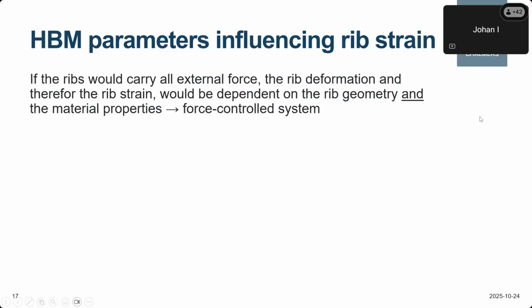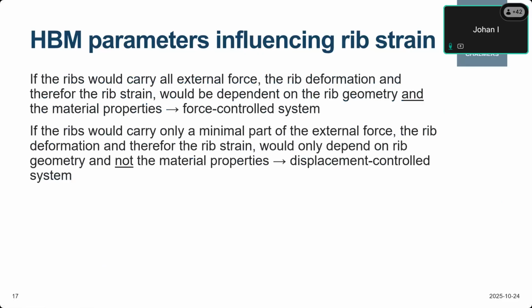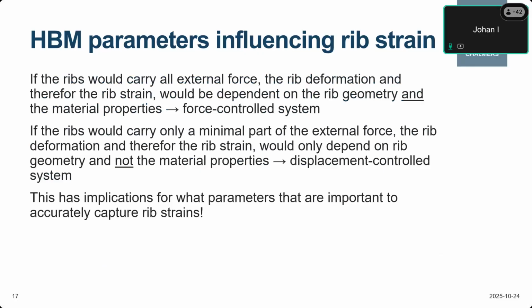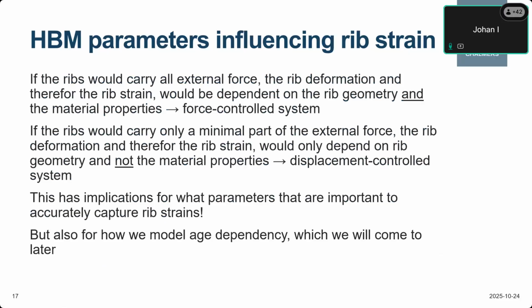So if the ribs would carry all external force, the rib deformation and therefore the rib strain would be dependent on the rib geometry and the rib materials. And then we could call that the force control system. The other thing, if the ribs would carry only a minimal part of the external force, then the rib deformation and therefore the rib strains would only depend on the rib geometry and not the material properties. And this would then be a displacement control system. And this has implications for what parameters are important to accurately capture rib strains, but also for how we model age dependency, which we'll come back to later.